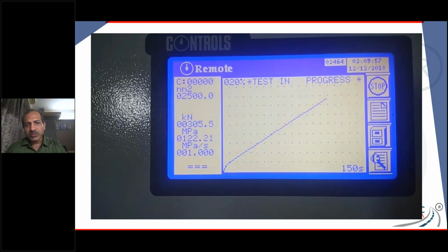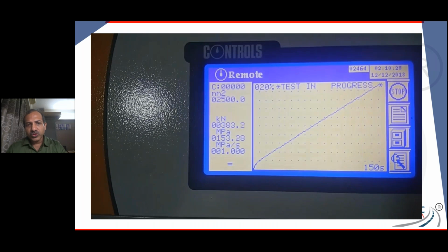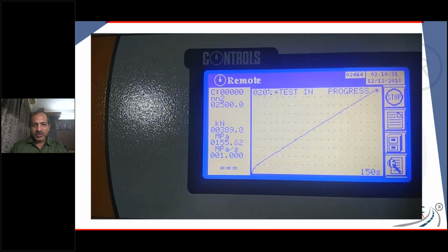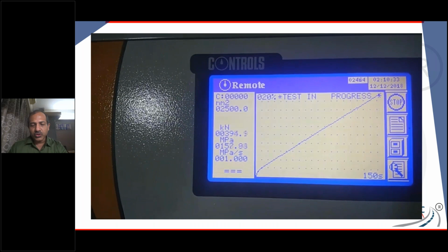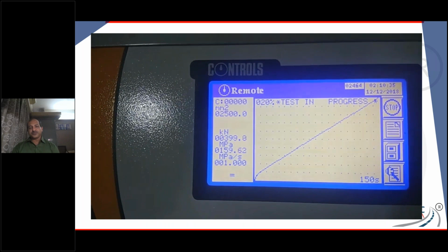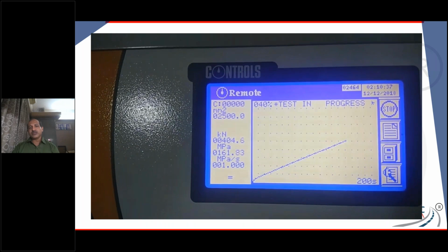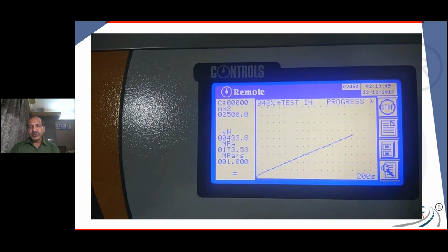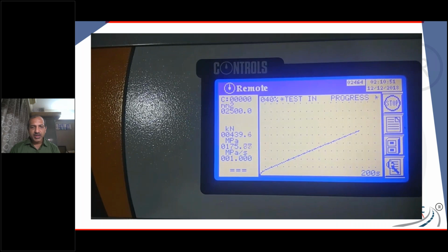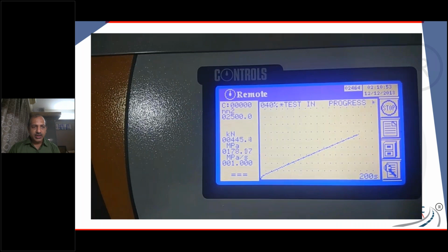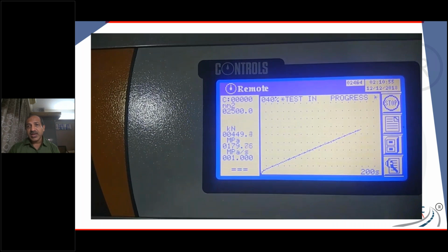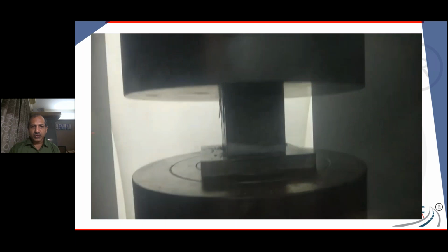So here I'm showing a cube. This cube is very small, about 50 mm by 50 mm by 50 mm. And you might ask, why this smaller cube? For all practical tests, you could use a 50 mm cube, and then you can confirm that with a 100 mm cube. So all initial tests can be done with 50 mm, but you might want to do your final results using 100 mm.